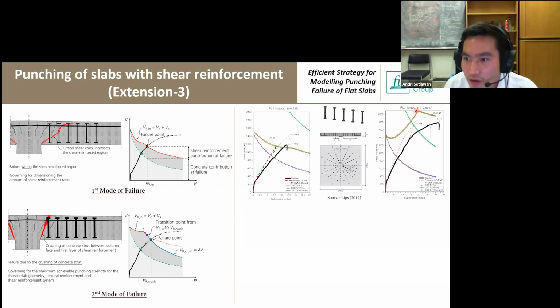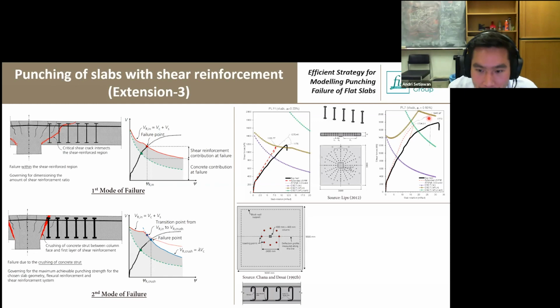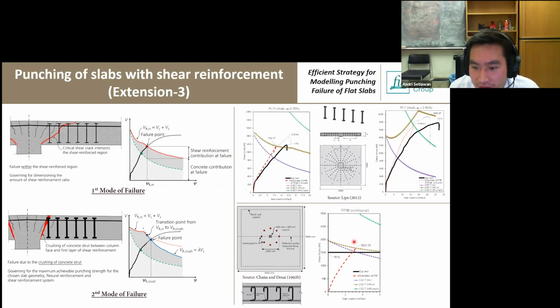And for the second scenario, we have the PL7, where the reinforcement ratio is 4 times higher. So in this case, the failure is governed by the crushing of the concrete. So interestingly, with this failure criterion, we are not only able to capture the punching capacity, but also the correct failure mode. And the last test that we did was a continuous slab tested by Chana and Desai. It's quite an old test from the UK, where they used one-leg stirrups. And this represents a slab supported by the contraflexure region. So you have some continuity here. You have positive moment. So we can see that the red curve is the prediction and the black curve is the test results.